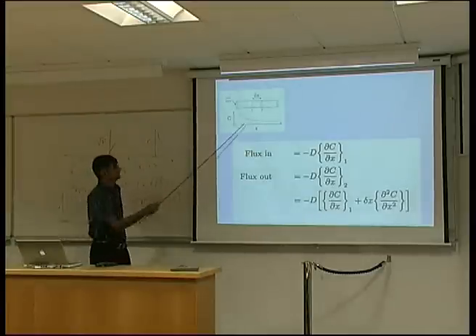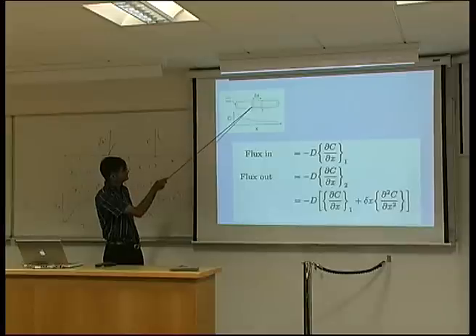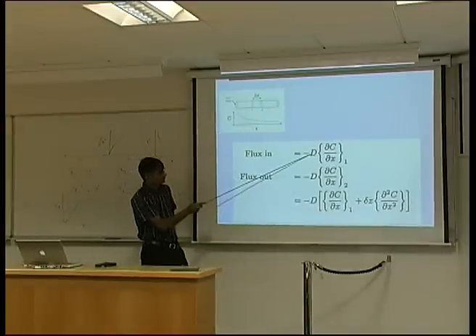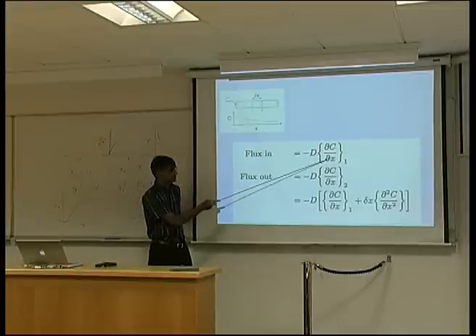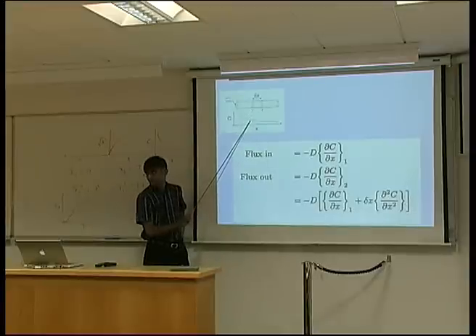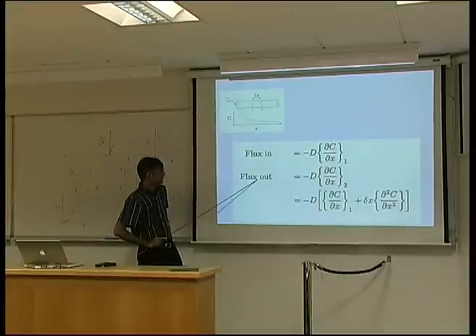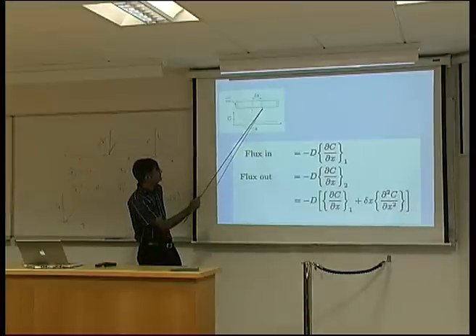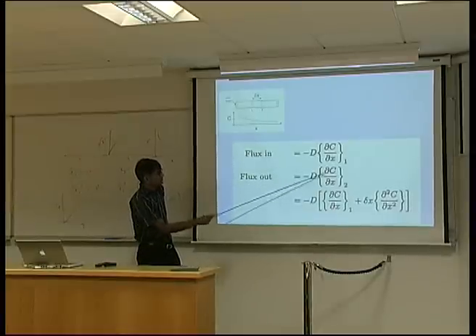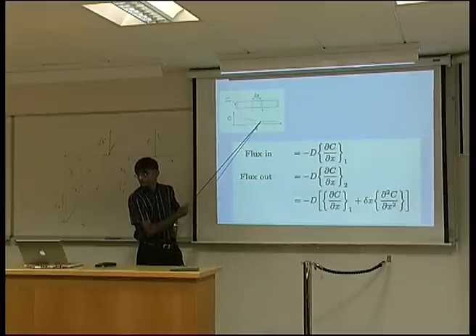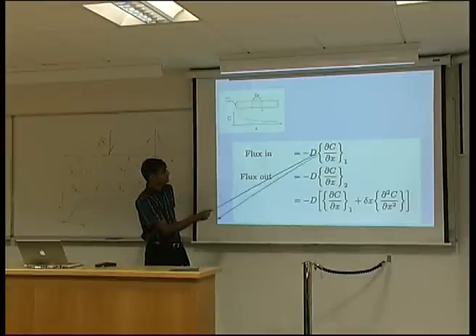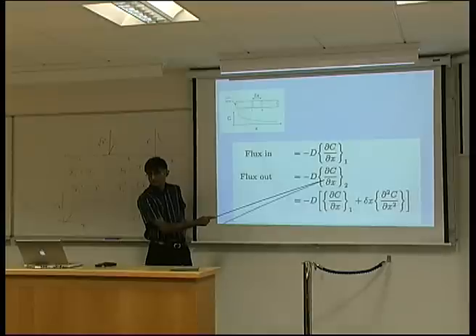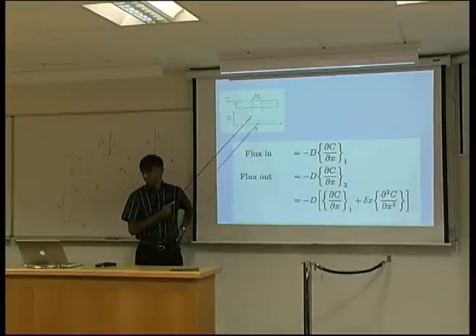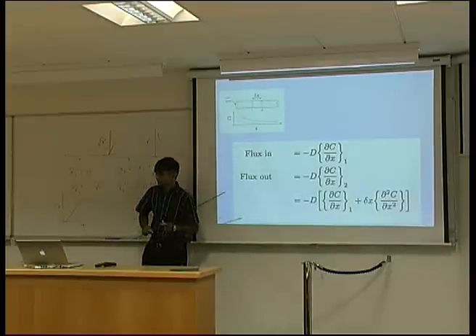Okay, so again, looking at that diagram, we'll look at the flux going into plane 1 and the flux into plane 2. So into plane 1, we have the diffusion coefficient times the gradient which exists at this point. Okay. Similarly, with Fick's first law, for this plane, we have diffusion coefficient times the gradient which is different now. It exists at this point 2, right? These two are no longer identical. We have here a curve instead of a straight line. Stop me if you don't follow, alright?